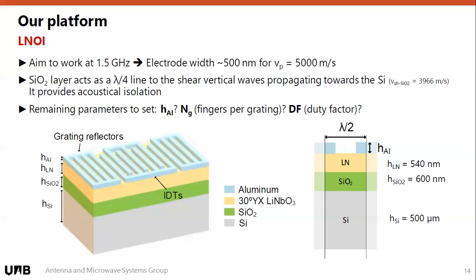So we call it the LNOI because we have lithium niobate on insulator. So we have this yellow thing here, our lithium niobate layer. Then we have a thin silicon oxide layer that is actually behaving as an impedance inverter for the waves that might be propagating towards the silicon. So it's isolating our layer from the substrate. Because when we are exciting the shear horizontal mode on the plate, we might also be triggering shear waves that are traveling vertically down towards the silicon. That's going to be energy leaking from your resonator, so it's going to be energy that is being lost. Your Q goes down. With this layer, we are actually isolating the substrate from our thin plate. So this is actually something pretty important.